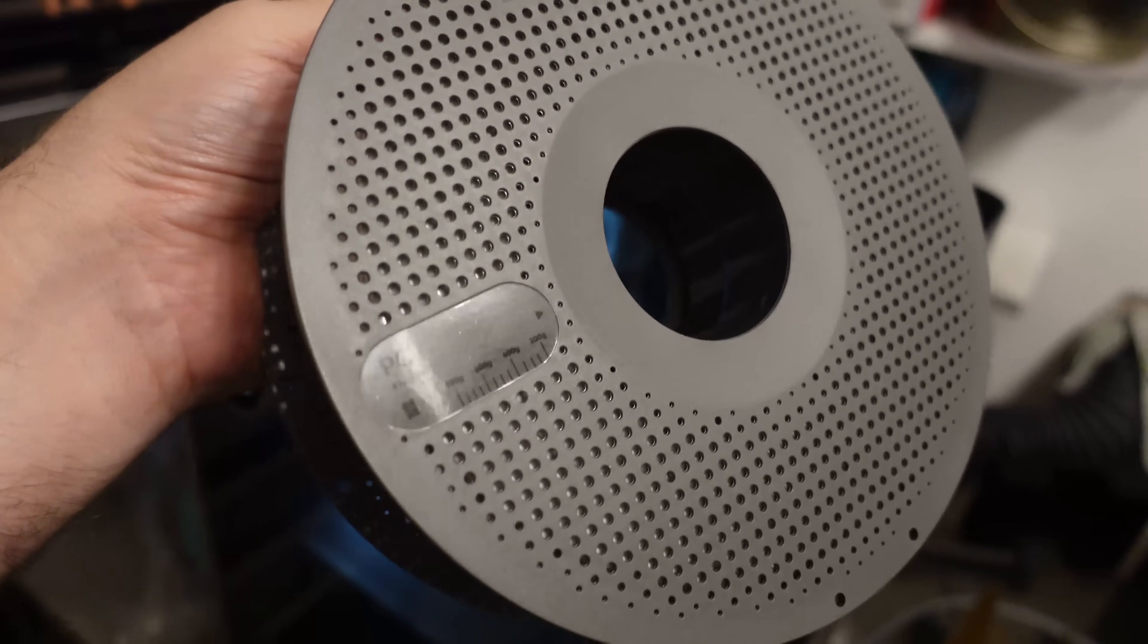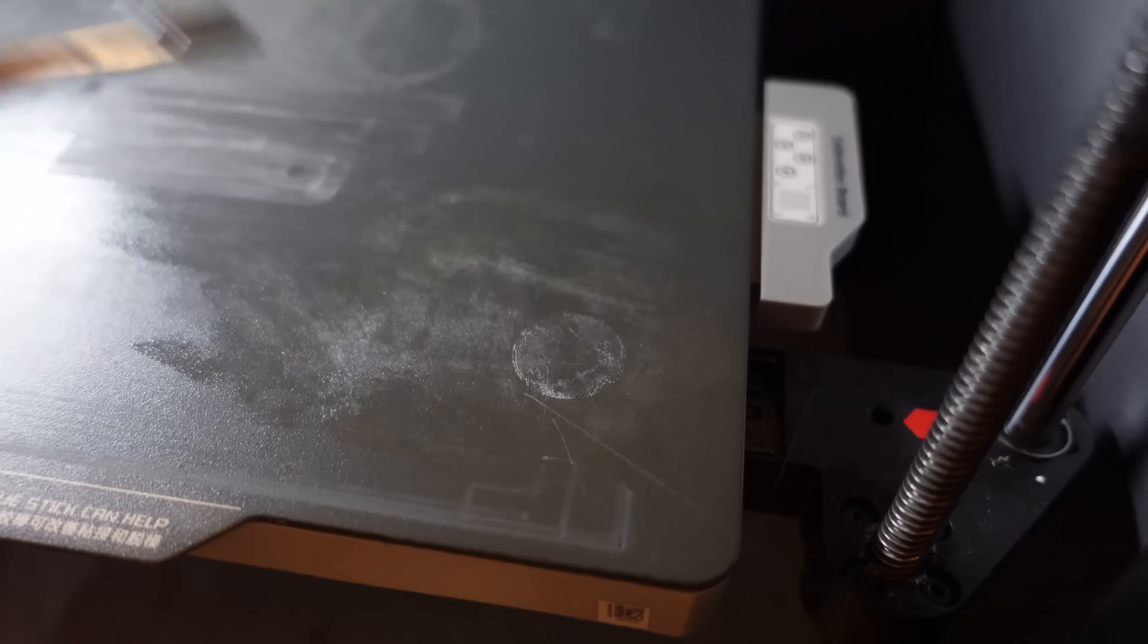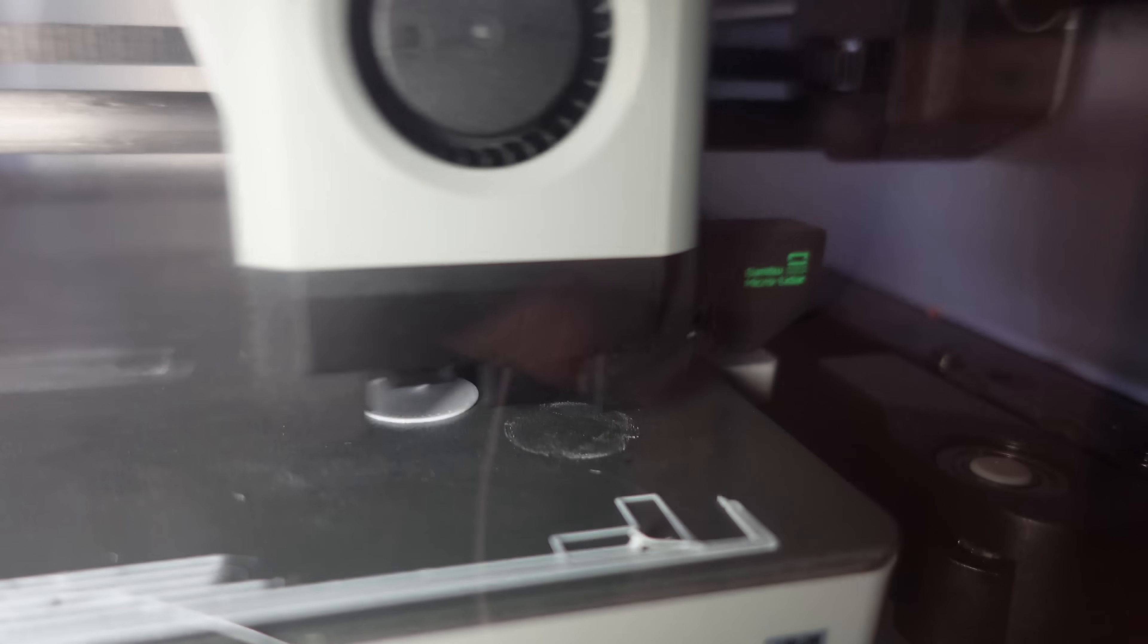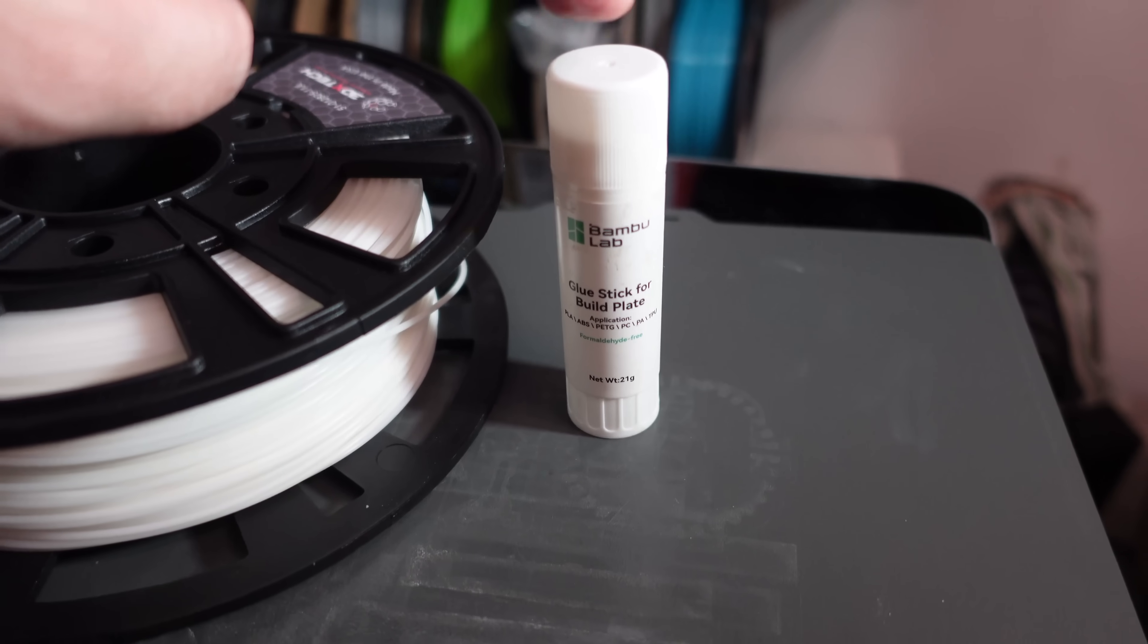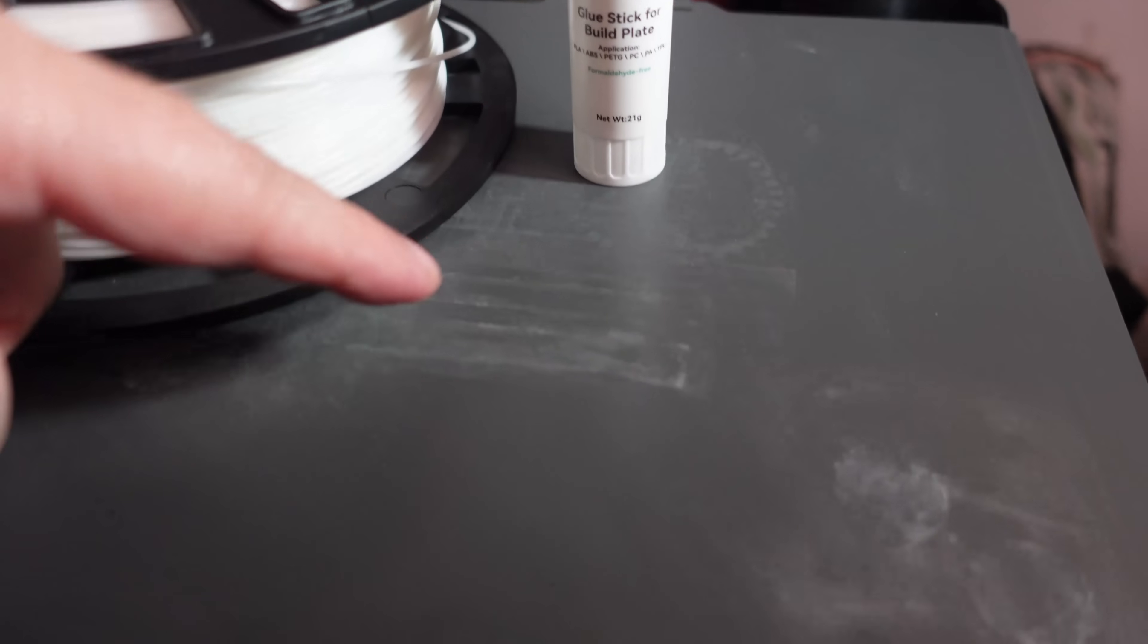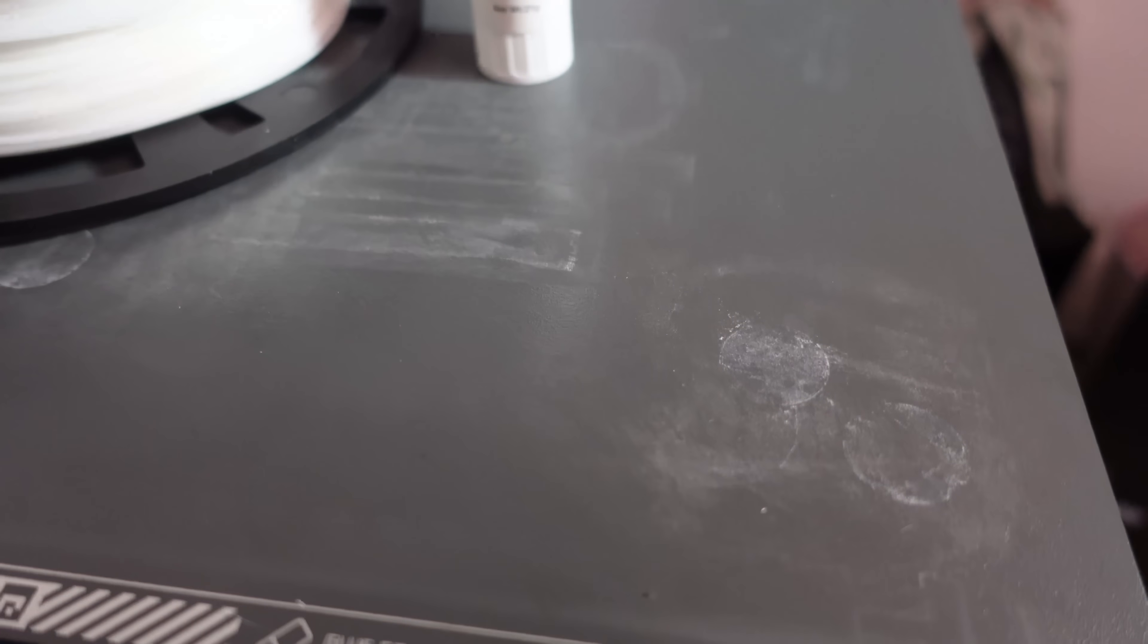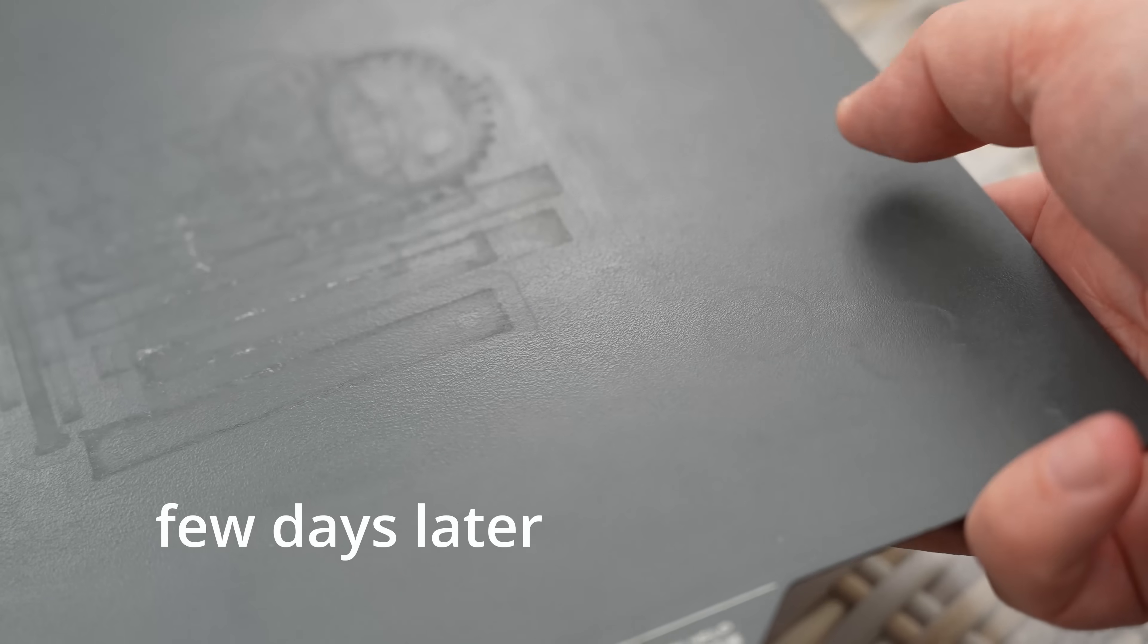So let's try to use the glue, but with polycarbonate, which has the same print temperatures. Bambu Lab polycarbonate. And I want to print another disk exactly here. I added fresh layer of the glue. It will finish in one minute and then I can analyze it. And it's fine. Okay I have a very stupid theory, but it looks like that somehow this Bambu Lab glue reacts with this PVDF, which is not too good for this engineering plate and leave those marks. And I have no idea how to confirm or check this. And this is how it looks like now. This is the damage. This was the polycarbonate and it's fine. And here was the gear for example. So the situation is not that bad now, but it's time to move to mechanical testing.